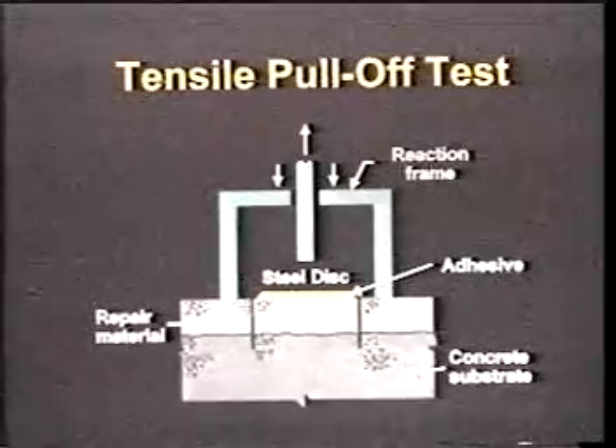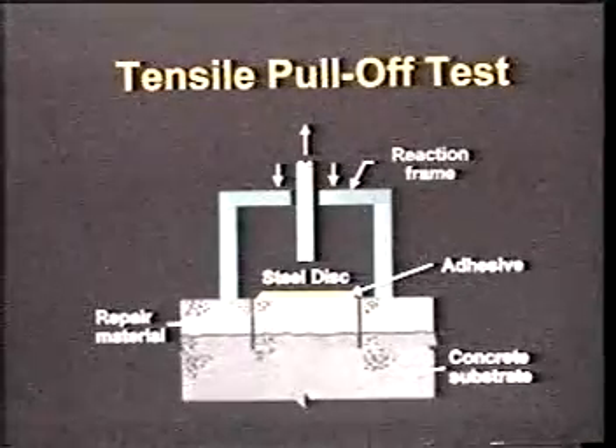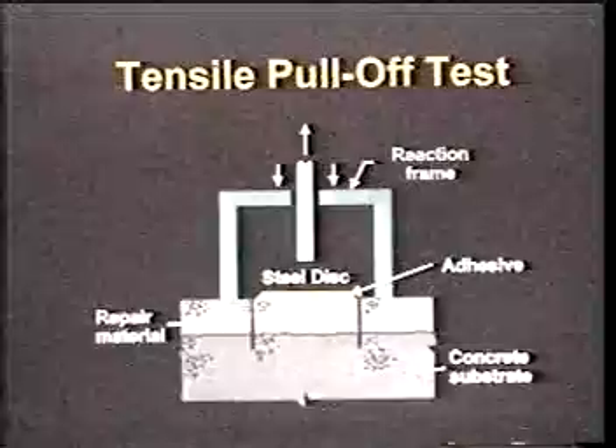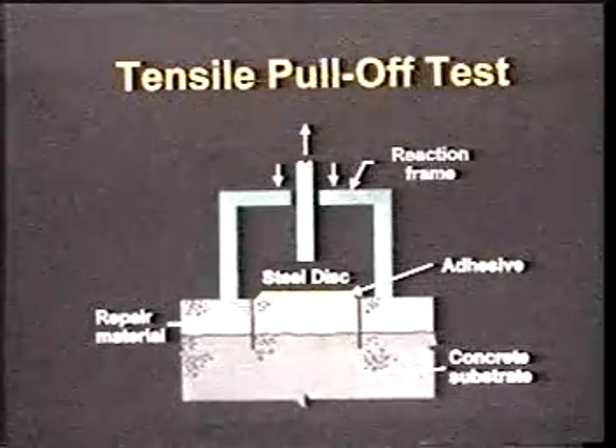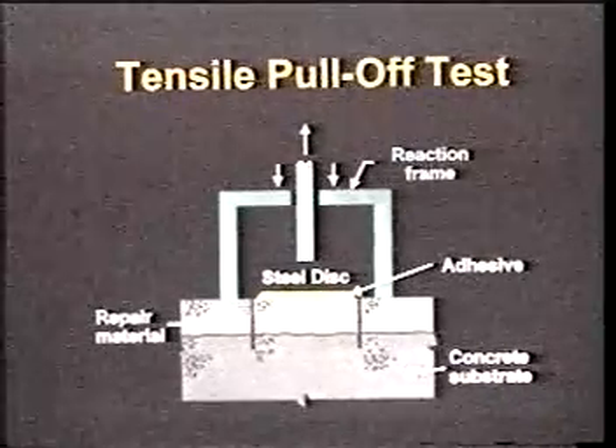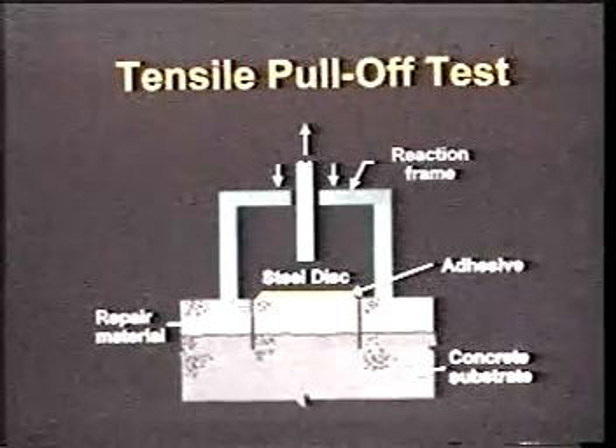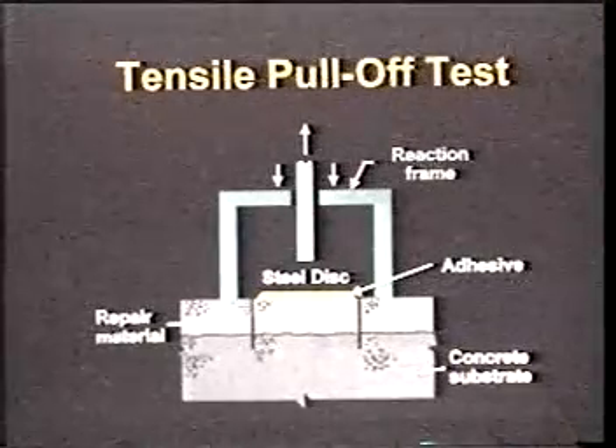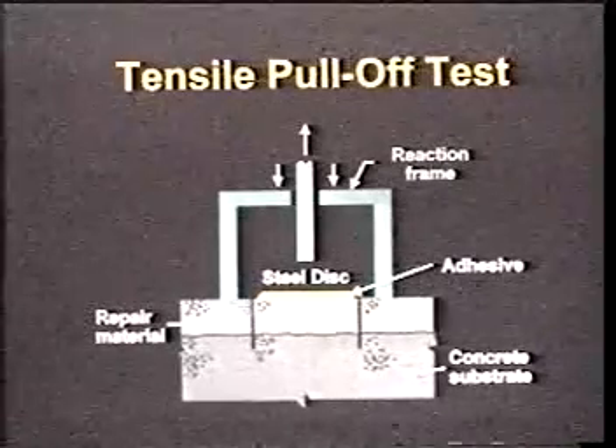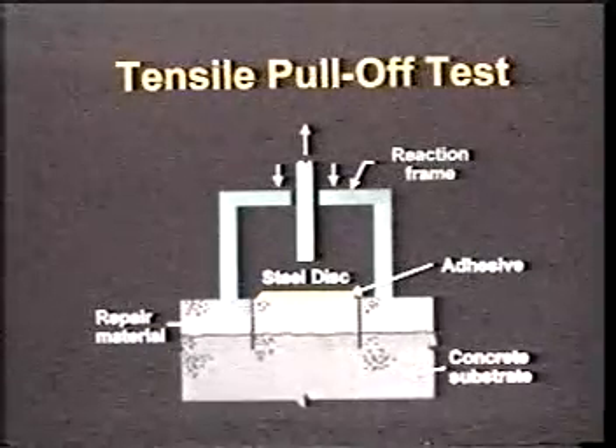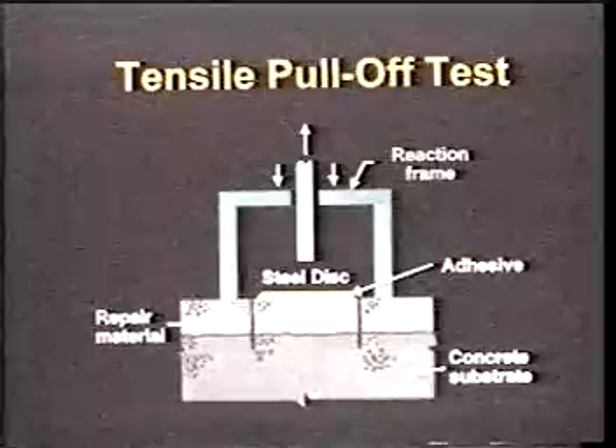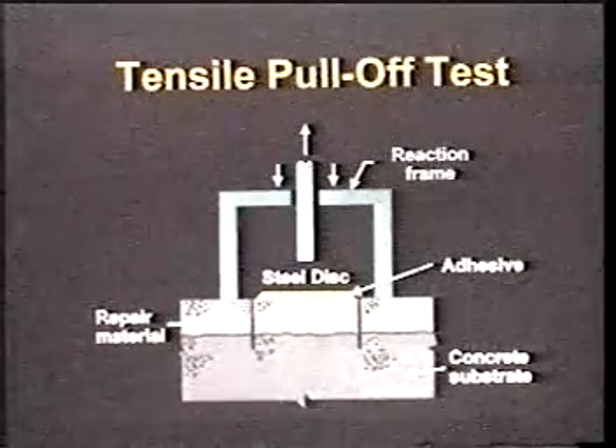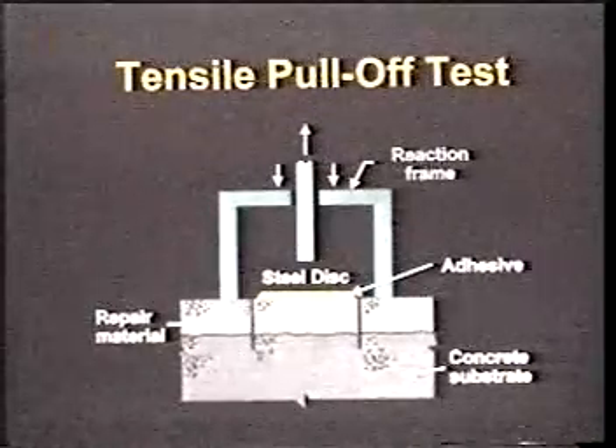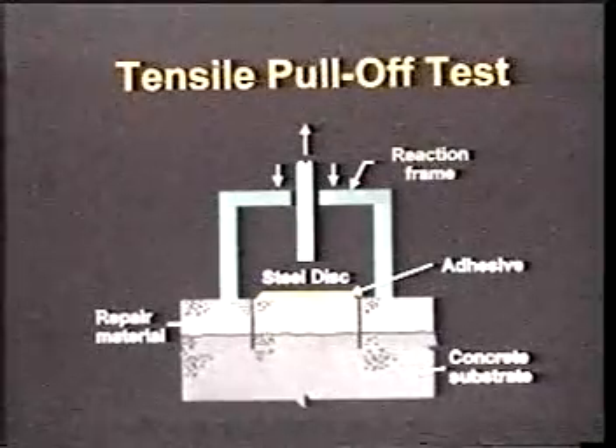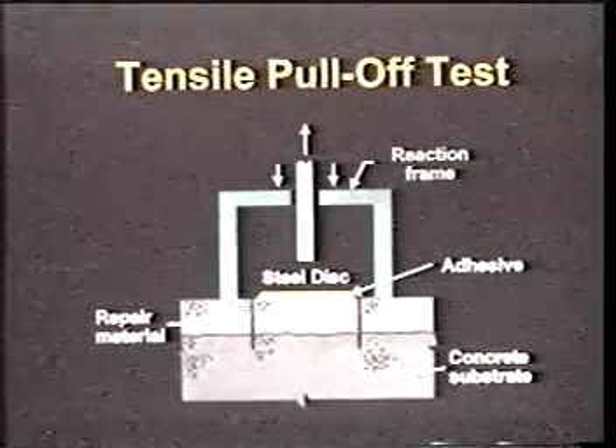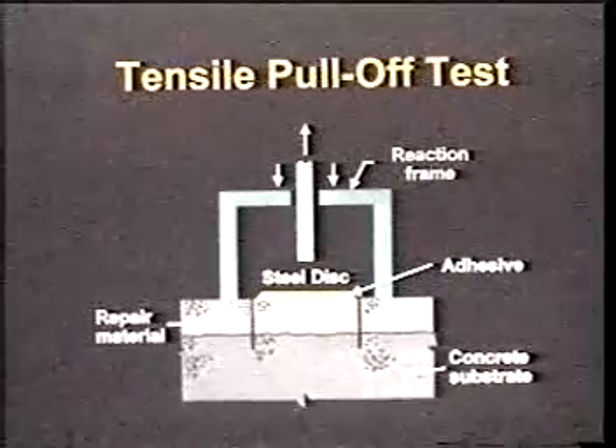Because when you have volume changes in a repair material which is applied, as I mentioned, in semi-liquid condition, you have in one layer, let's say it is a layered system, compression, in another layer you have tension, and the stresses occurring at the interface are actually shear. But still, over the years, the industry found that this is the easiest, most representative test for field evaluation.